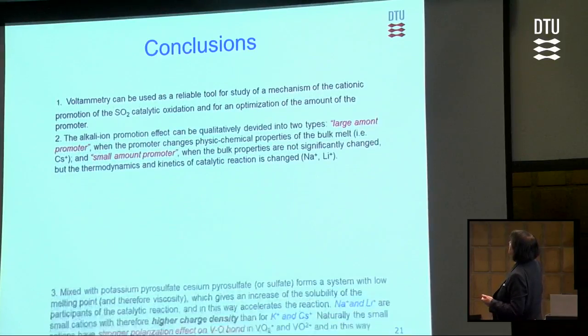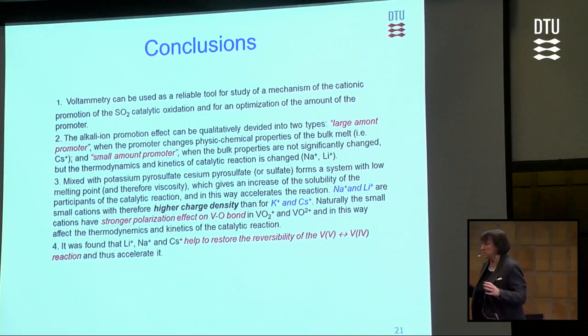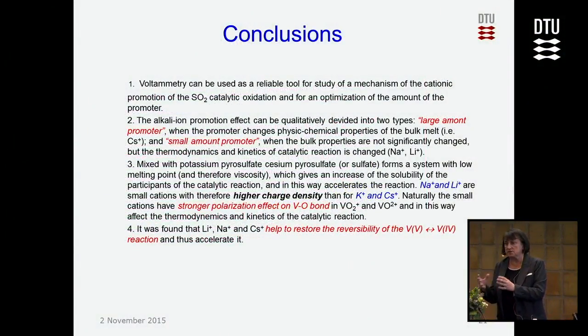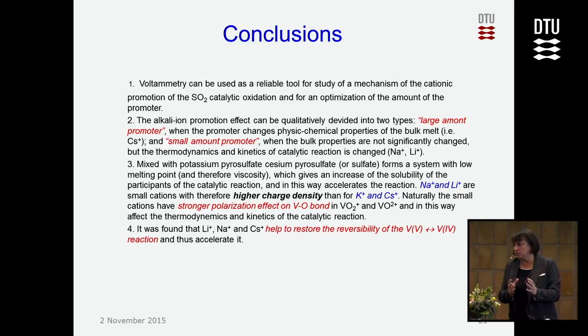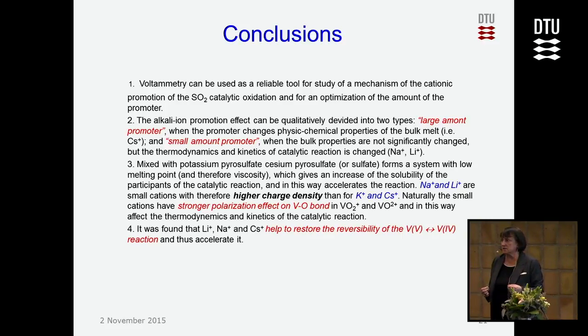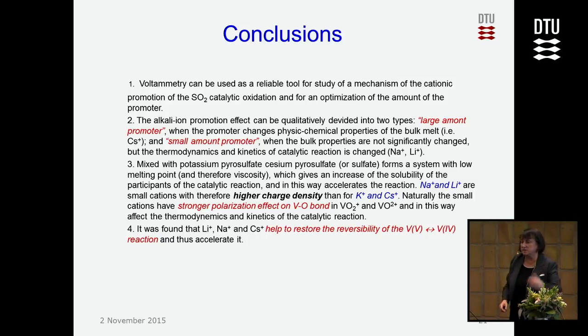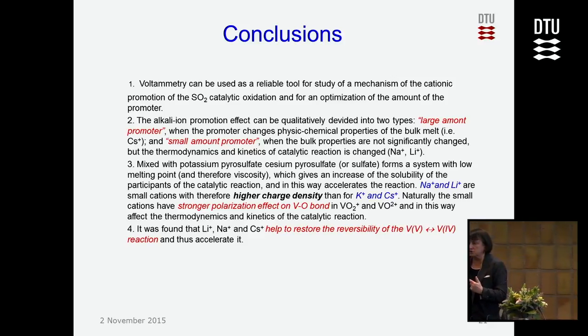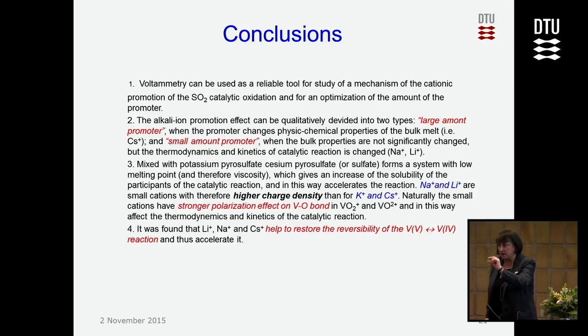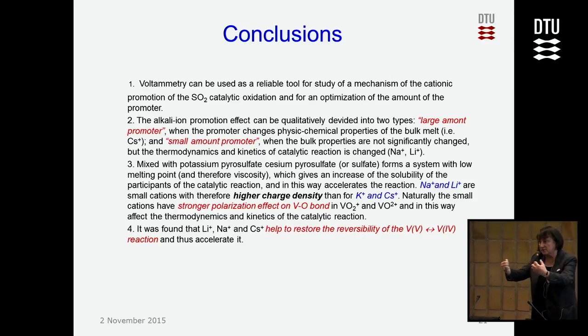Okay, conclusions. I'll do it fast. So there are so-called big amount promoters and small amount promoters. Big amount, like cesium, it's 1 to 1 and so on. What is their effect? Their effect is that they change physicochemical properties. So with cesium, we have a decrease of melting point, better solubility of products and reactants. That's why cesium is usually added in big amounts. With small ions like lithium and sodium, these are small cations. They have high charge density, so they polarize the vanadium-oxygen bonding and make it easy to destroy it.